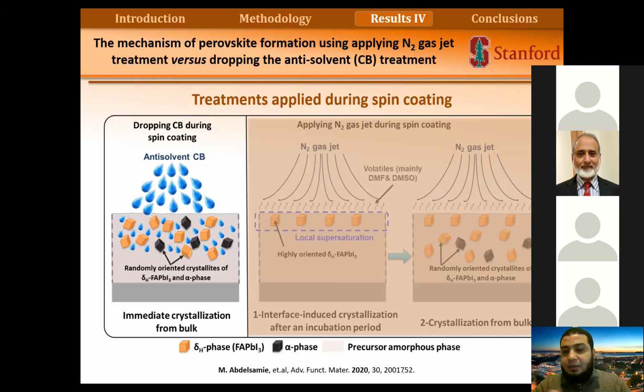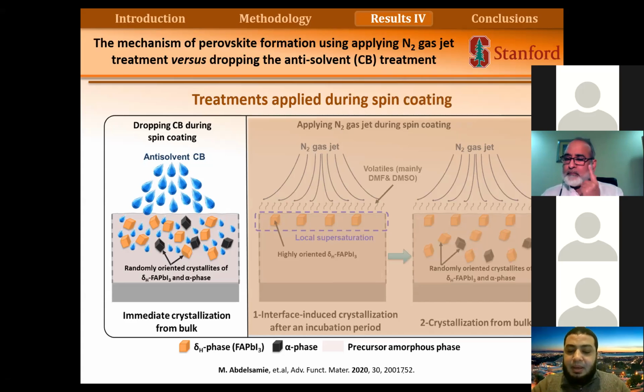So we were working on different projects. They studied stability, and we studied the film formation. The stability can range from months to 2 years based on the choice of the material. It can be stabilized as we mix the compounds. If you just use the pure compound, like pure cesium, pure FA, or pure MA, the materials are not stable at all. But when you mix cations or mix anions, then you can improve the stability.